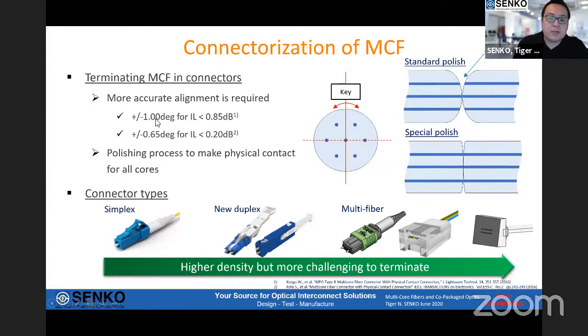But this alignment tolerance should include how we align the fiber into the ferrule, the connector ferrule itself, as well as, if you are using fiber optic connectors, there will be tolerance coming from the different components. So there are lots of things to be discussed to make good insertion loss using multi-core fiber. And also polishing is not something we can see as an easy way, because if we use a typical UPC polish to achieve the better return loss, the fiber end face will be like this, and there can be air gap. So it's not so much special, but we need to consider a suitable polishing approach to have all the cores make physical contact.